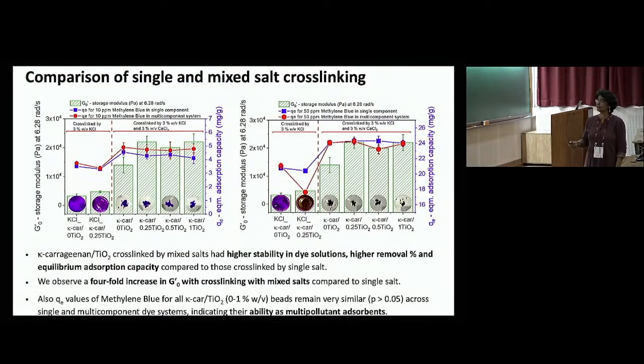So this is with no calcium chloride. But once you add calcium chloride, you are able to form these nice solid beads which do not disintegrate, and you can take them out and use them as an adsorbent material. The reason, since I did not mention it, why we encapsulated TiO2 was that the undergraduate student did a lot of photocatalytic experiments as well. That's the reason we chose the TiO2 particles.